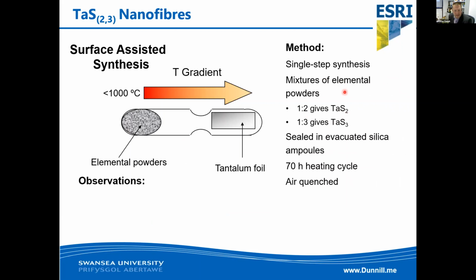If we use a 1:2 ratio of elemental powders, we can actually form the tantalum disulfide. If we use a 1:3, we can form tantalum trisulfide. If we change the heating arrangements, we can actually get ribbons versus particles versus wires.